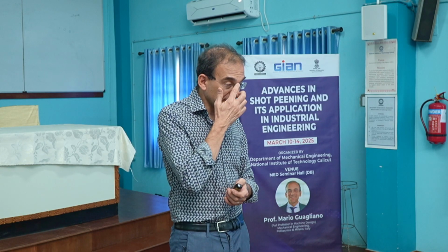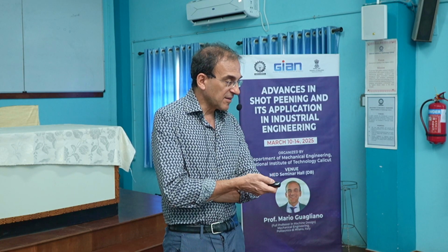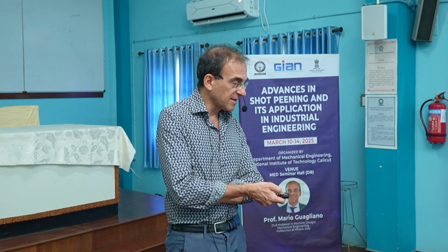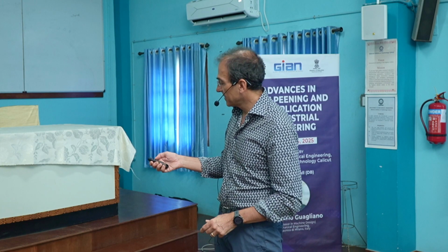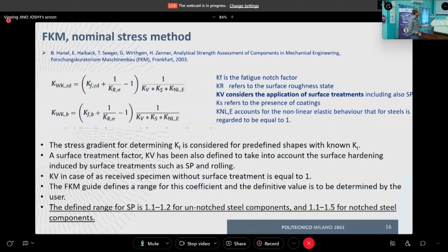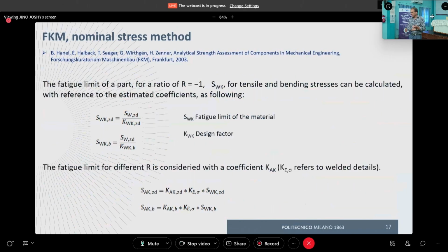And then, once we have determined this design K factor, for bending or for tensile load, we can calculate the fatigue limit of the part, starting from the fatigue limit of the material and dividing the latter by means of this design factor. And if you have a welded part, we can use also other coefficients, or if you have a non-null mean stress, also R can be included with another coefficient.